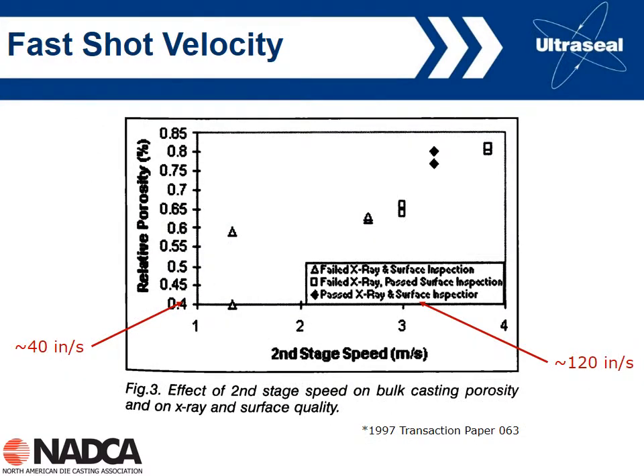Fast shot velocity, and again, here's some data from the 1997 transactions, the paper numbers given here. And now we're looking at the impact of fast shot velocity on porosity. This is really independent of whether we're talking about cold chamber or hot chamber. And in some ways, maybe these data are a little bit confusing, because it's certainly different than what we've heard from NADCA for years. What it's showing, or what it seems to show, is that the lower the fast shot velocity, the lower the porosity. It's quite significant. You go from 0.8% porosity up here at high speeds to 0.4 to 0.6 at the lower speeds.